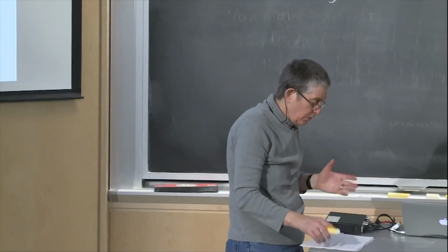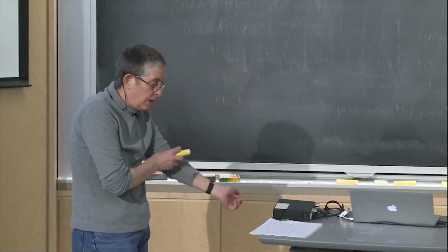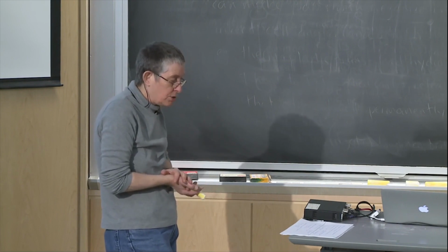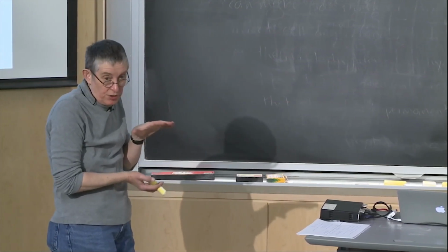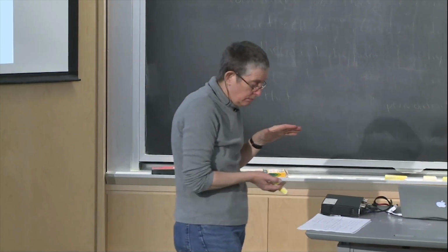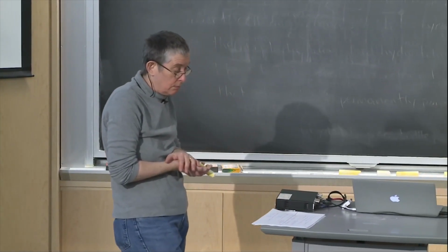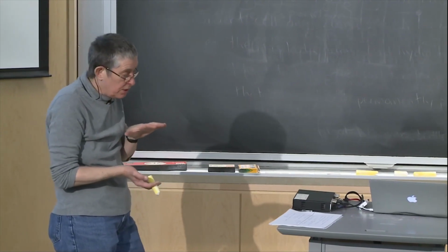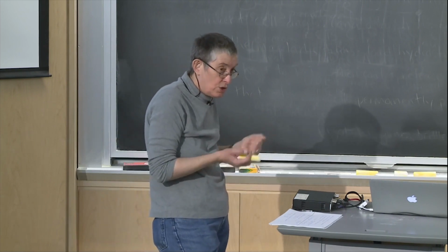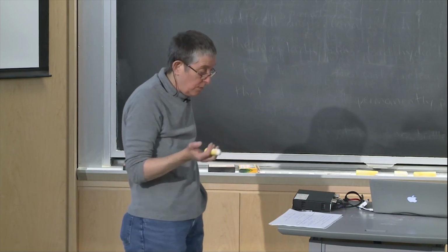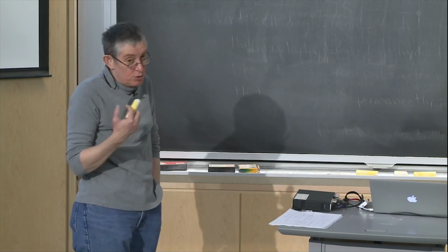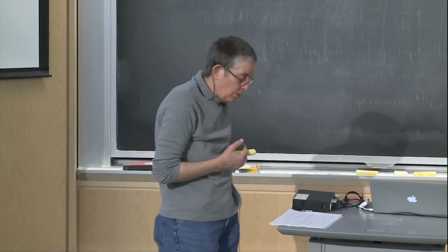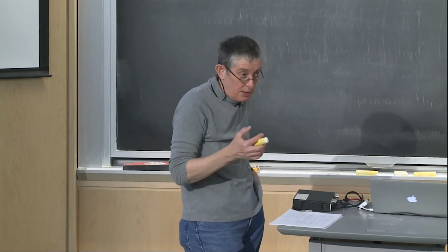So the idea here is we say we've got a cubic element of the foam, and initially it has a volume V naught, and if we apply a uniaxial stress, there's some change in the volume of the foam. So there's some volume V after we compress it by some strain epsilon. If we can figure out what the volume is relative to the initial volume, we can figure out how the amount of gas changes from the initial state to the compressed state. And then we can use Boyle's law. So the idea is P1 V1 equals P2 V2. Then we can figure out, using Boyle's law, what the pressure must be.